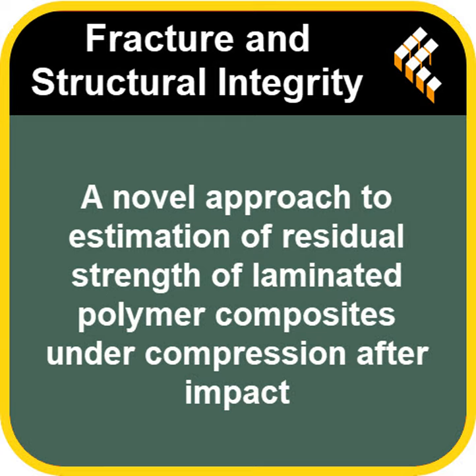And another really critical finding, something that's potentially huge for practical applications, they found a very strong negative linear correlation between the measured residual strength and the measured area of delamination inside the material. We're talking a correlation coefficient below -0.9, which is statistically very strong. Yeah, it means as the hidden damaged area, delamination, gets bigger, the remaining strength reliably goes down in a predictable linear way. So you could almost estimate the strength loss just by measuring that internal damage.